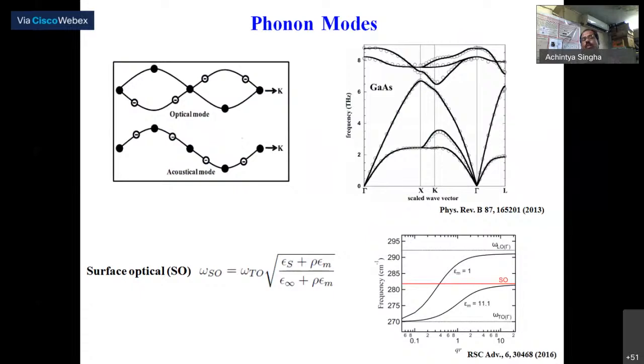These give rise to the phonon, which is the quantum of vibration. If you look at the phonon dispersion curve, for example for gallium arsenide, a semiconductor, at the gamma point, that is k equal to 0, the acoustic phonon mode goes to 0, but the optical phonon modes have a finite value at k equal to 0. Apart from the optical and acoustic modes, you also have the surface optical phonon mode, which appears at the interface between two dielectric media.